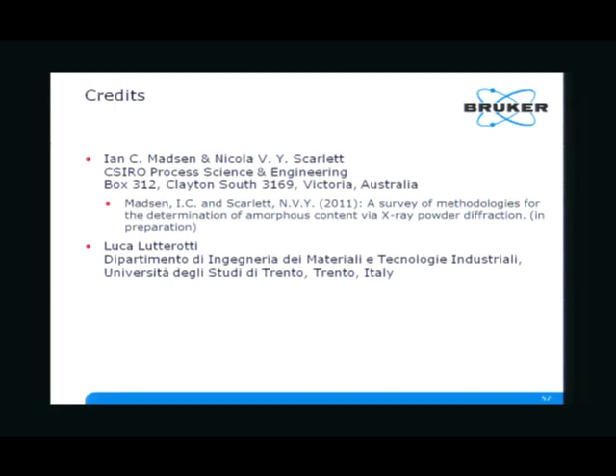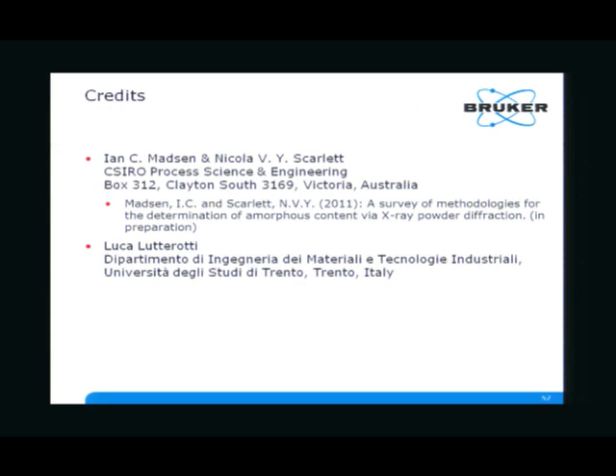Thank you very much. Are there questions? Let's get questions from Bob Von Dreele then. This is Bob Von Dreele from Argonne National Lab. One significant comment that's sort of missing from this is that any material that has a significant diffuse scattering component — that's going to wind up in the background — and as a result the quantitative phase analysis would be underestimated. Thank you very much, yes, indeed.